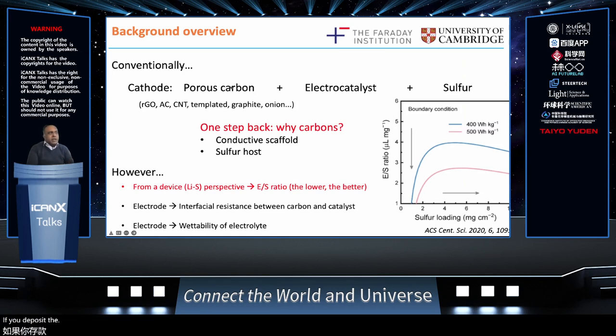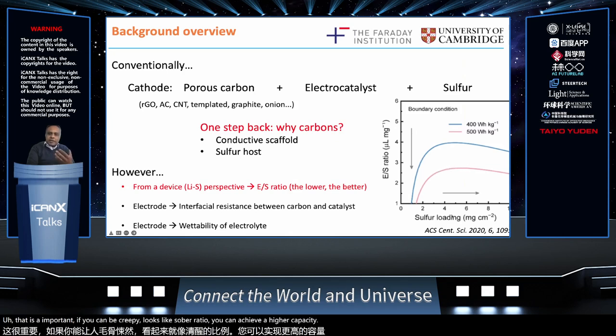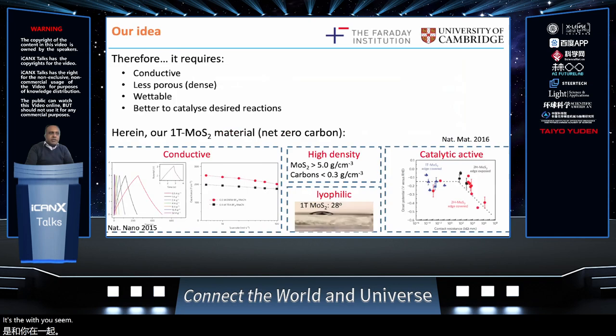If you deposit the electrocatalyst on porous carbon, then there is a serious resistance, right? The electrocatalyst is typically an oxide or non-conducting material. And so the charge has to be transferred from the porous carbon to the electrocatalyst, which can introduce serious resistance or interfacial resistance. And also, carbons are hydrophobic, and so the wettability with electrolyte is quite low. So this plot here shows that it's the electrolyte to sulfur ratio that is important. If you can decrease the electrolyte to sulfur ratio, you can achieve a higher capacity that is independent of the sulfur loading after a certain concentration. So adding more active material in sulfur does not really help. It's the reducing of the electrolyte to sulfur ratio that helps.